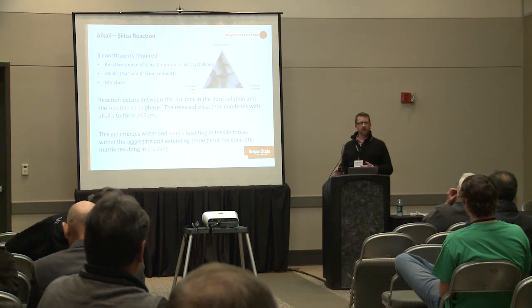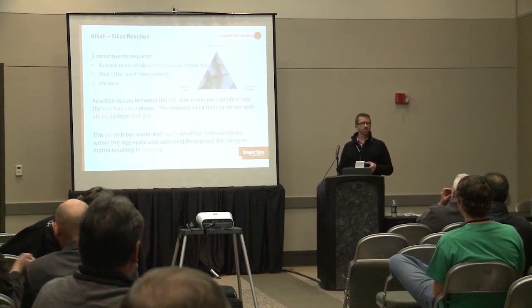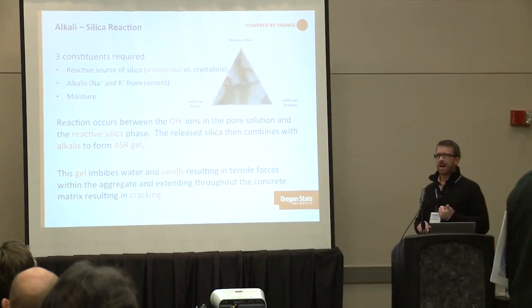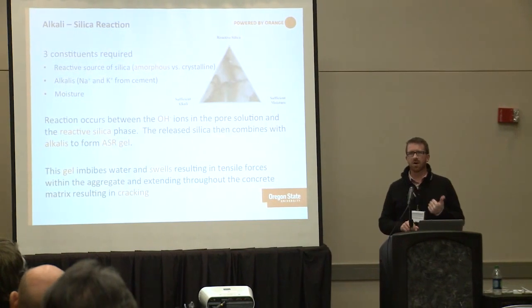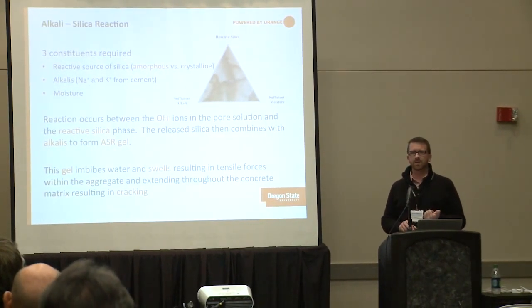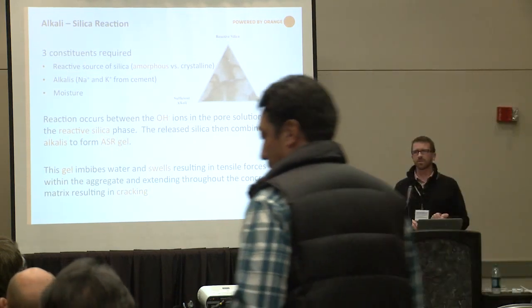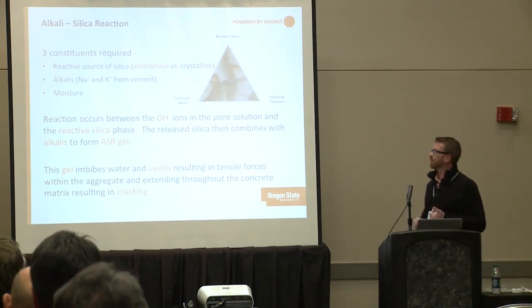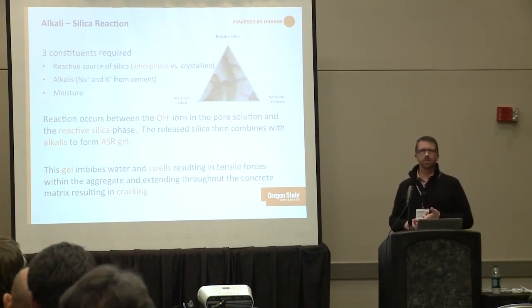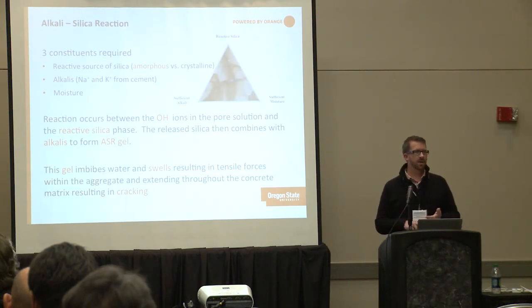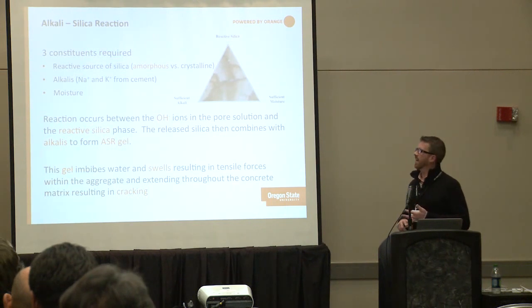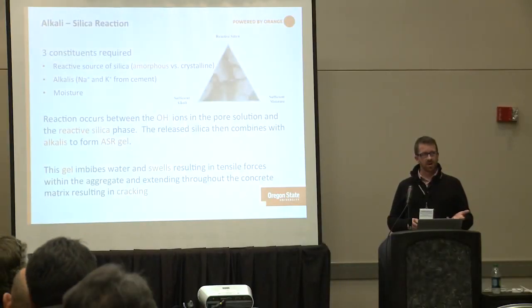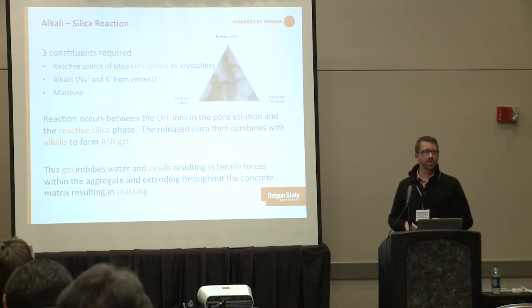For those unfamiliar with alkali-silica reaction: it is an internal reaction that occurs inside concrete. We need three main things for ASR to occur — a reactive source of silica in the aggregate, alkalis (which come primarily from portland cement, but also from aggregates and supplementary cementitious materials), and moisture. You need water for the reaction to progress.